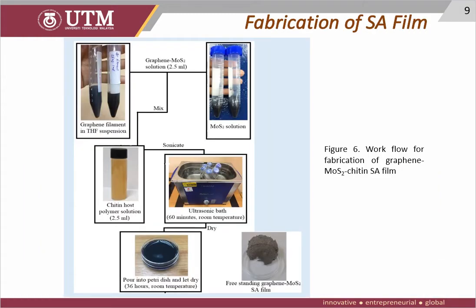Okay, this is the workflow for fabrication of the Graphene-MoS2 chitin SA film. We use 2.5 milliliter of Graphene-MoS2 solution and mix it with 2.5 milliliter of chitin polymer solution, and sonicate in an ultrasonic bath for 60 minutes at room temperature, and dry in a petri dish for 36 hours at room temperature. And then lastly, we got the freestanding Graphene-MoS2 chitin SA film.